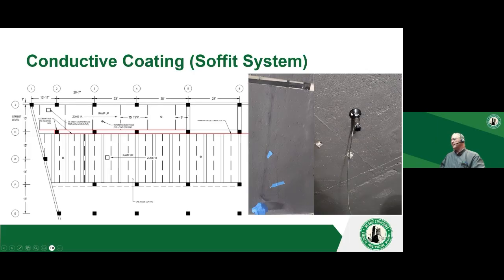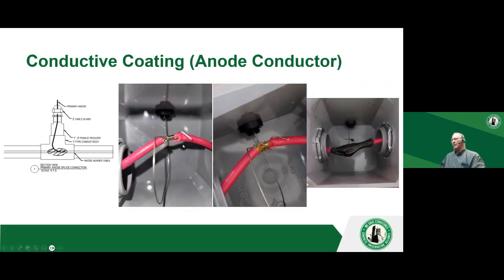And this is a bond test to make sure the coating was applied properly. You want to do that as part of the QC. You want to make sure your wiring connections are good. Typically, you're having a tight platinized titanium wire that is crimped. Cover it with grease, and then you tape it. It's very, very straightforward.